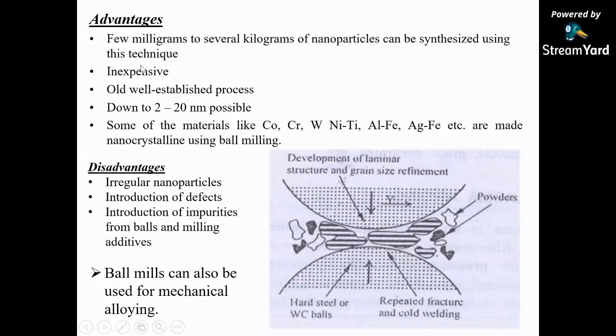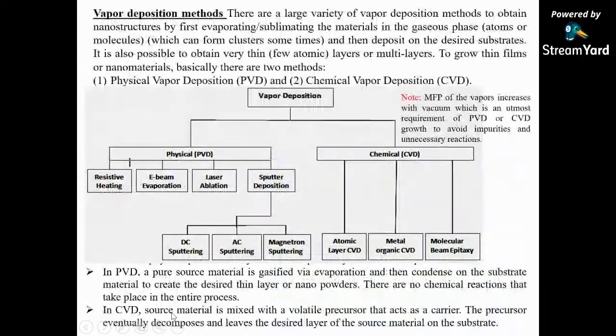So the few advantages are like this: few milligrams to several kilograms of nanoparticles can be synthesized using this technique, it is an inexpensive, old, well-established process, and sizes down to 2 to 20 nanometers are possible. Some materials like cobalt, metals and some alloys one can make by this ball milling. And of course, there are some defects and irregular shapes, and this also can be used for mechanical alloying.